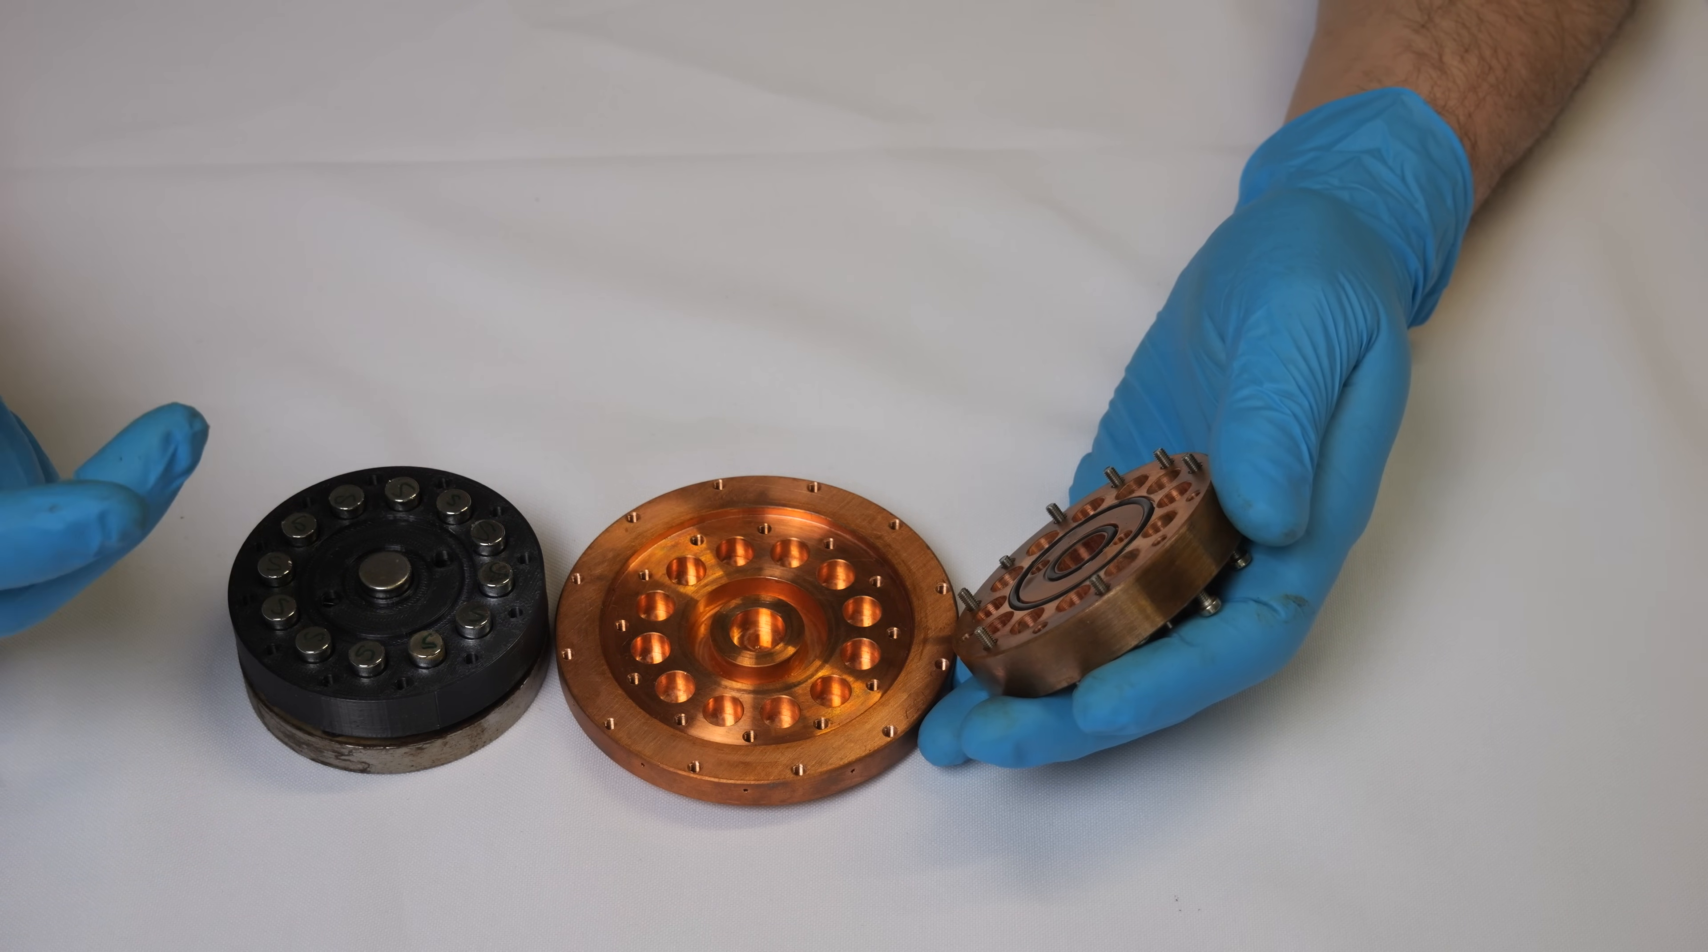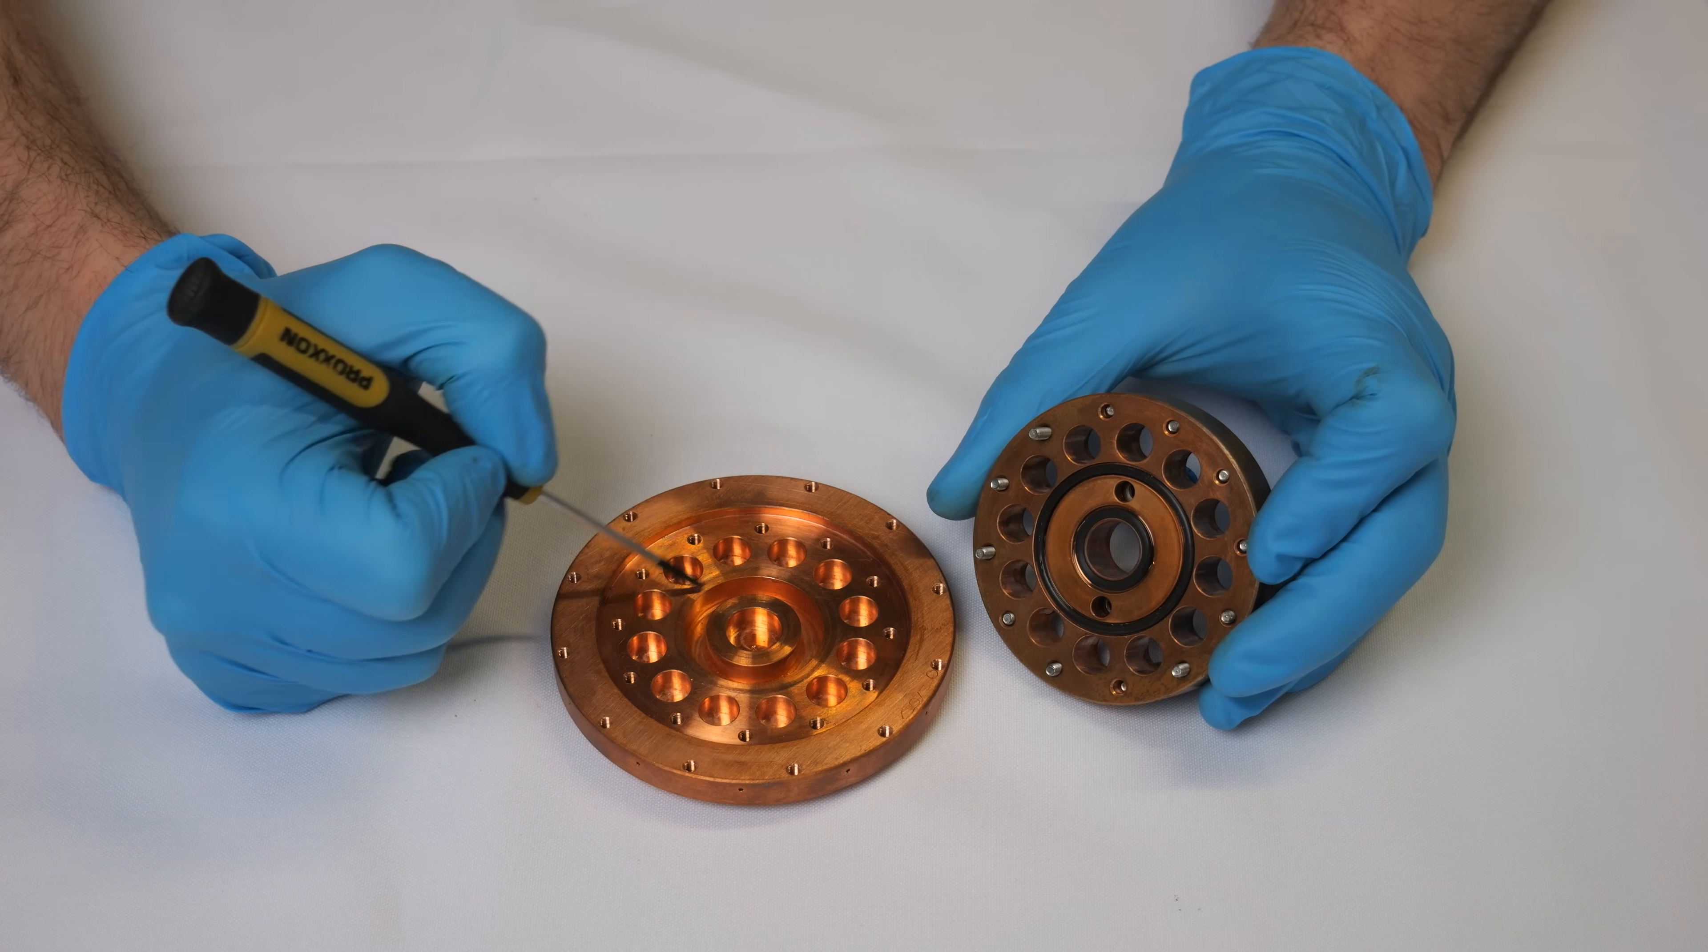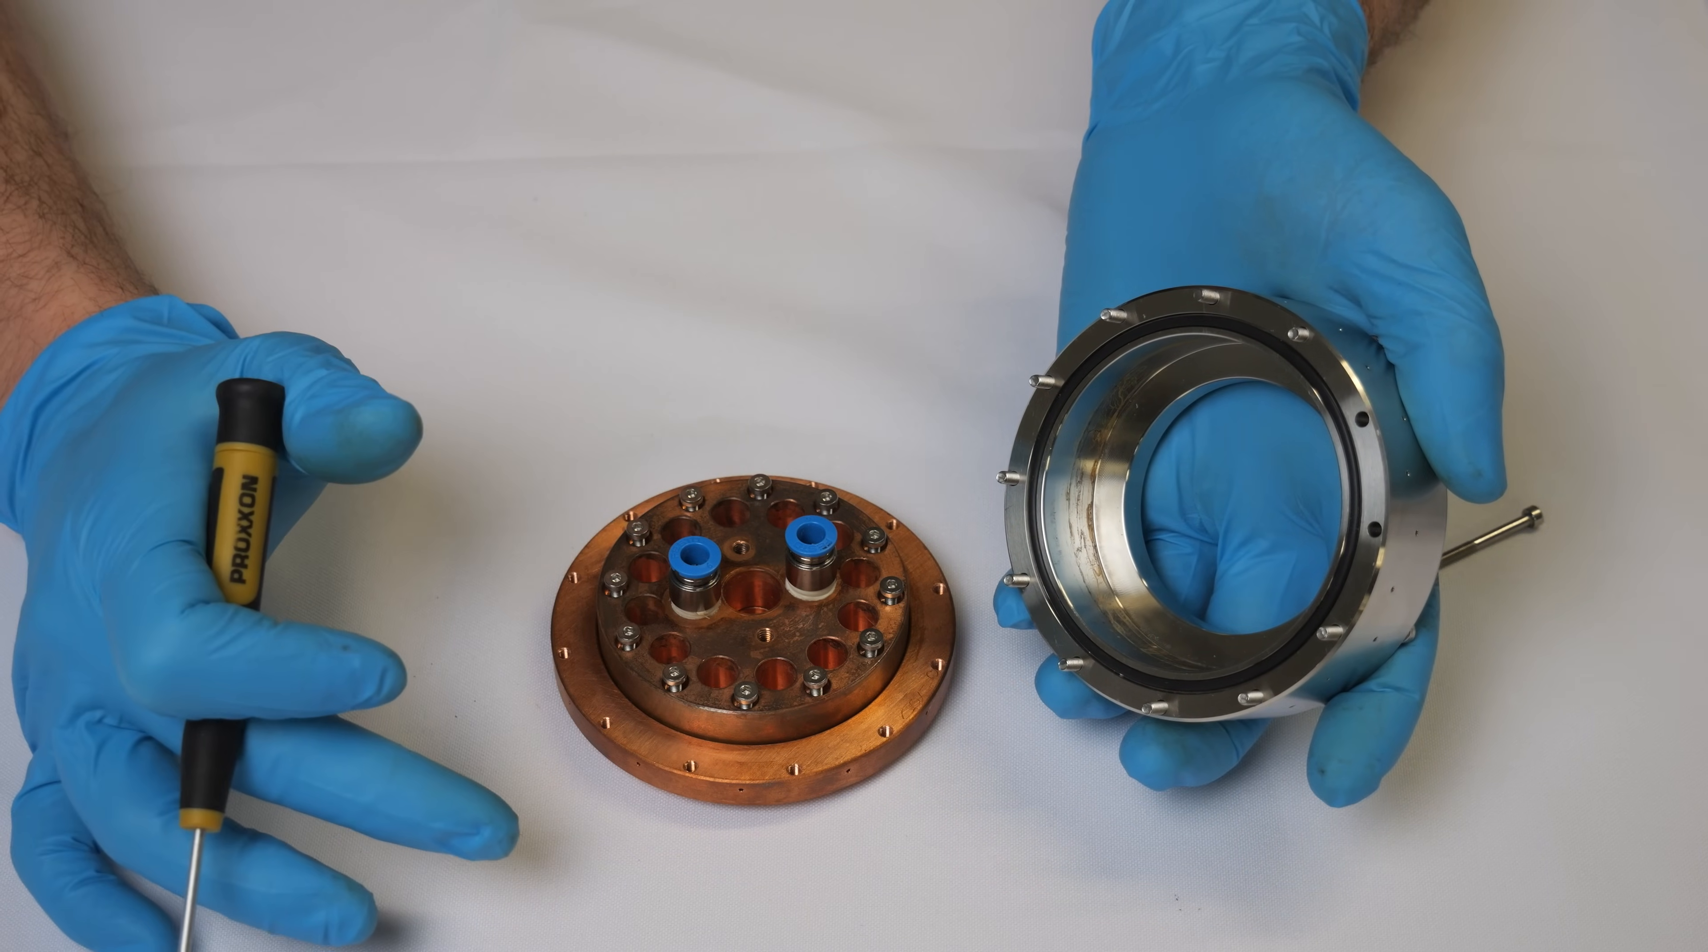Another important fact is that the cooling channel is sealed with the inner o-ring against the inner magnet and with this outer o-ring against the outer magnet. There is a third o-ring which is the o-ring that sits around this part right here which seals against this copper surface. Which means that we have two o-rings between the water channel and our vacuum. That is important because o-rings will over time saturate with water and the water will then diffuse out of the o-ring in your vacuum chamber. Which means you always want two o-rings between the water channel and your vacuum.